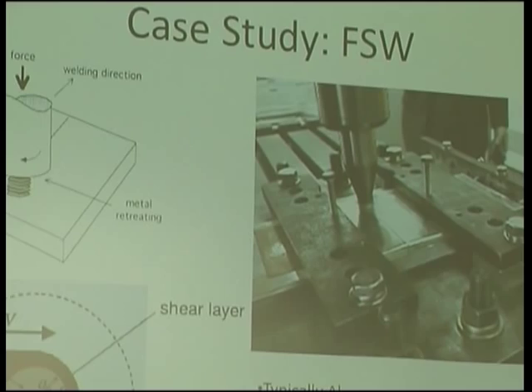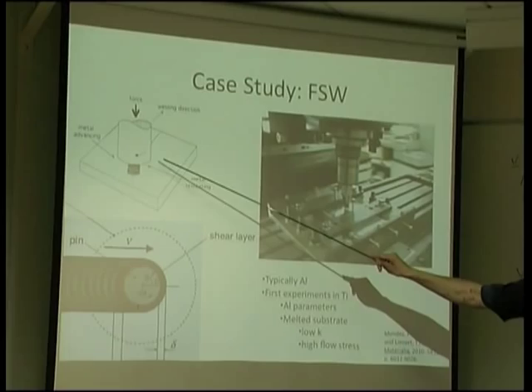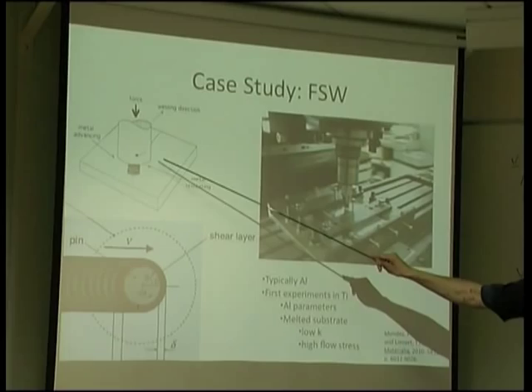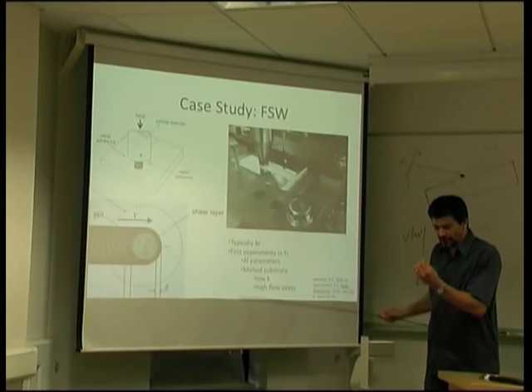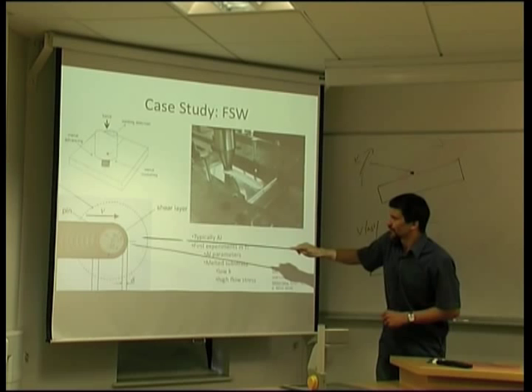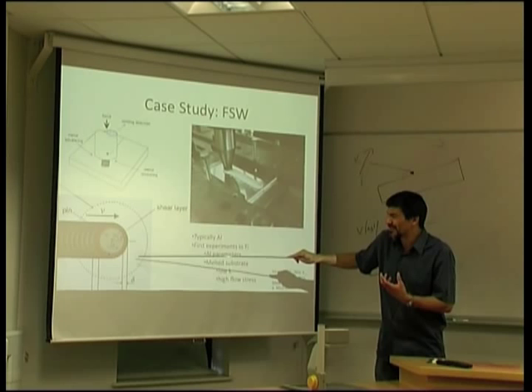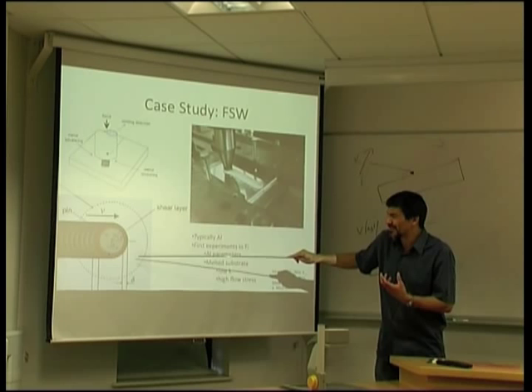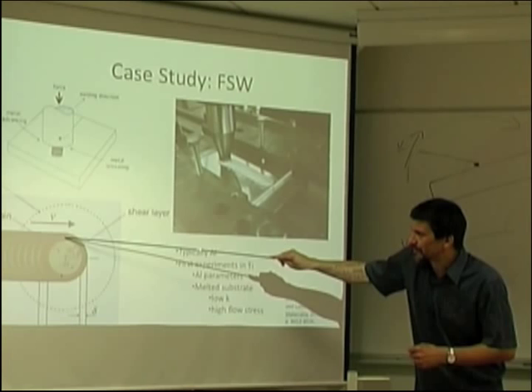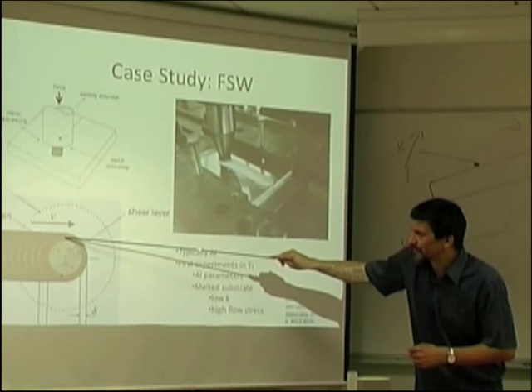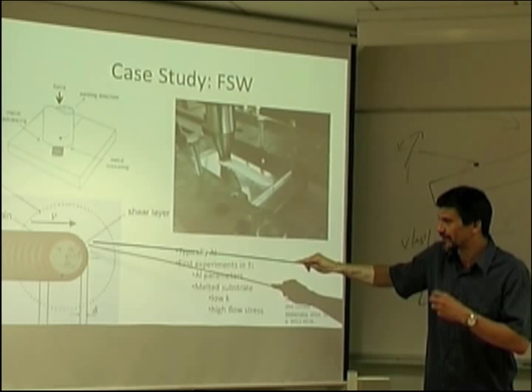In friction stir welding, it's a solid-state joining process that is based on very severe plastic deformation that generates localized heat. The localized heat softens the material, and that's the way you constrain this hot and soft area. Here you have this video, here you have a little schematic of a rotating tool that you get to see here, that as it rotates, it deforms the material. And if you were to look at it from here from the top, you would see this is the pin, this part here, or this part here that was moving, that is solid and is steel, typically, often the substrate is aluminum. This is what this process is good for.